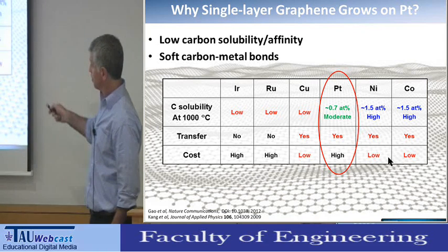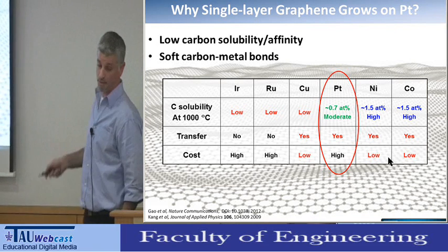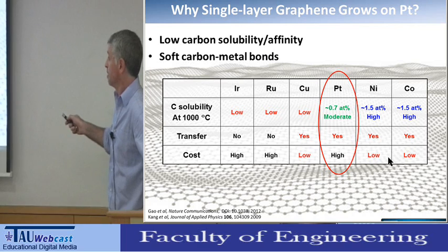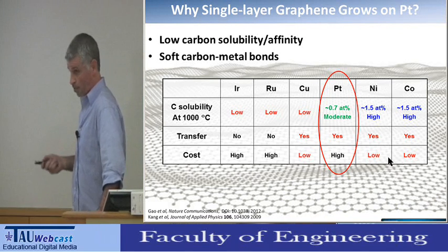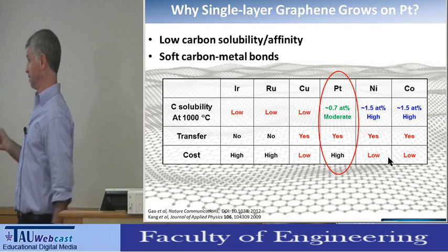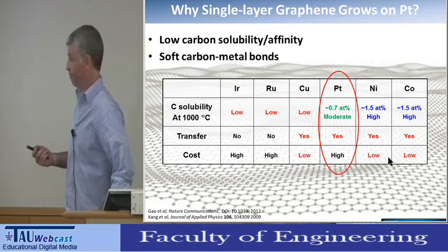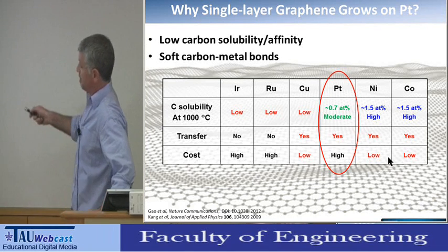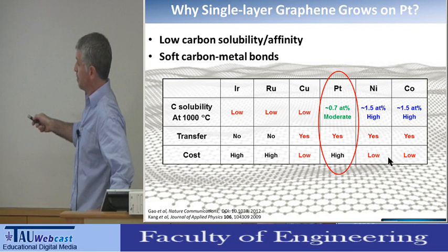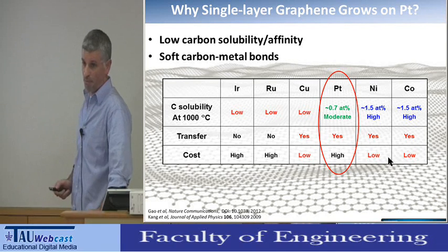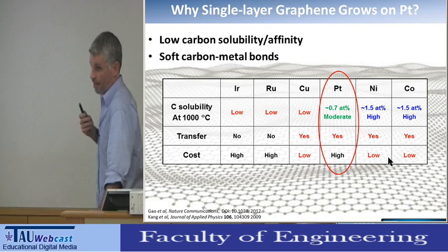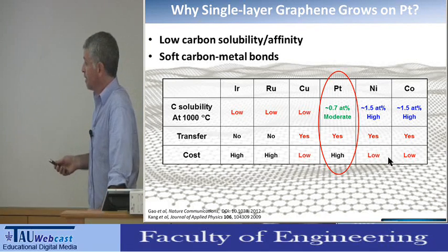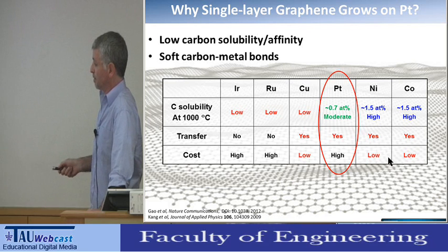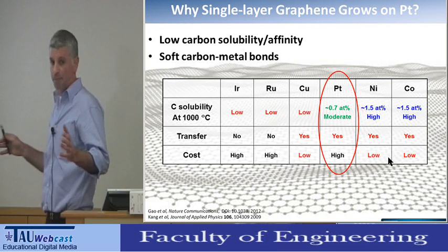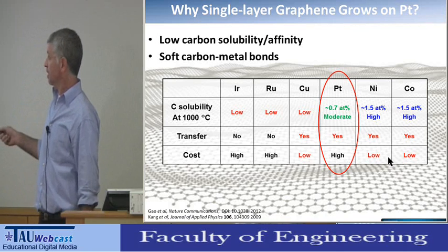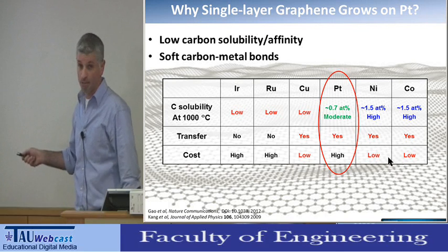Then you have the other most common materials, which are nickel and cobalt, that have a relatively high carbon solubility, and that's why it's so hard to control the number of layers with these materials, and you usually get few layers of graphene. But then you have in the middle platinum, which has a moderate carbon solubility, which is enough to give you a few layers or thin graphite, but in fact it can be shown that at a very wide parameter regime you can get single layer graphene on platinum.